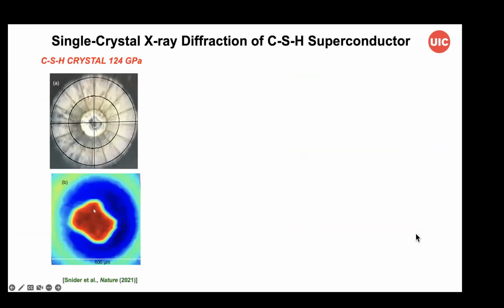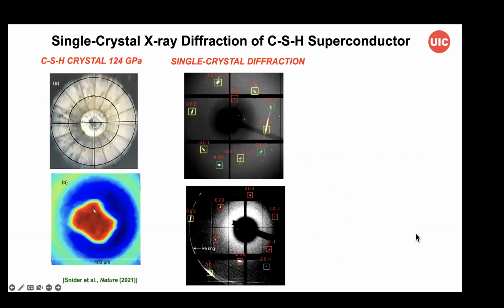In collaboration with Ranga's group, we looked at some of the very same samples that they had studied in their initial study of the high TC materials, and measured X-ray diffraction over a range of pressures where equivalent samples show superconductivity. These were single crystal measurements conducted at the APS. These are images of the sample there on the left, and then some selected diffraction patterns.